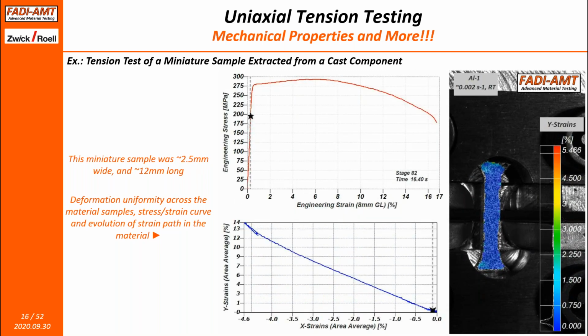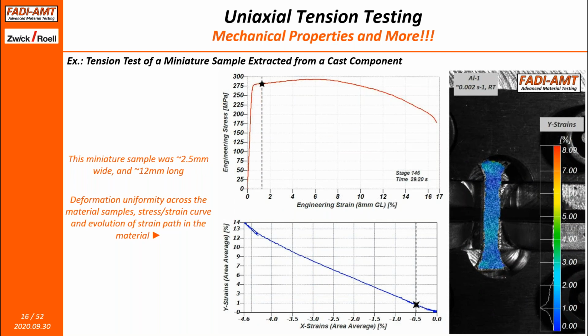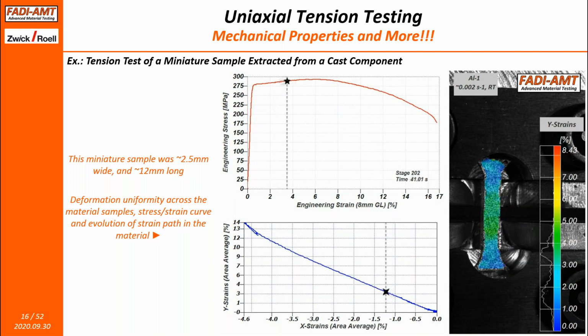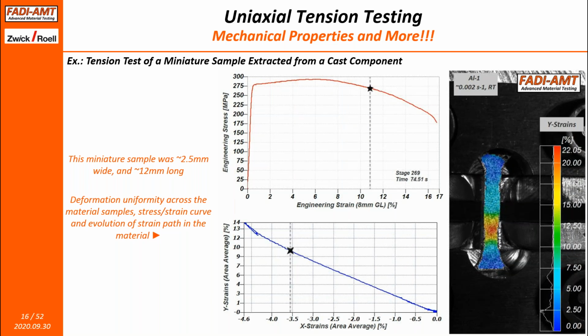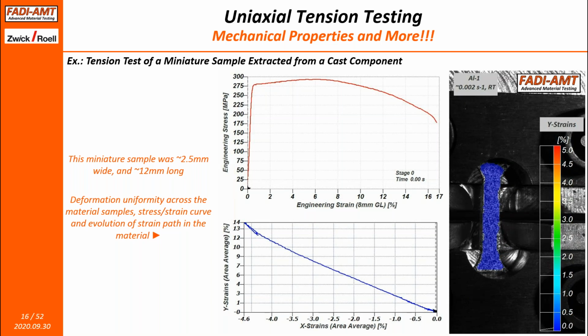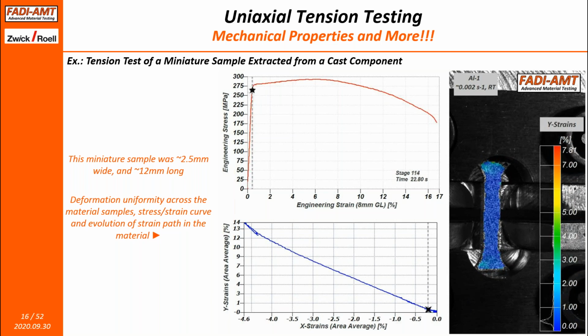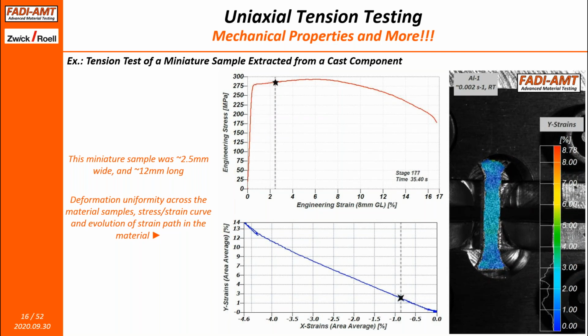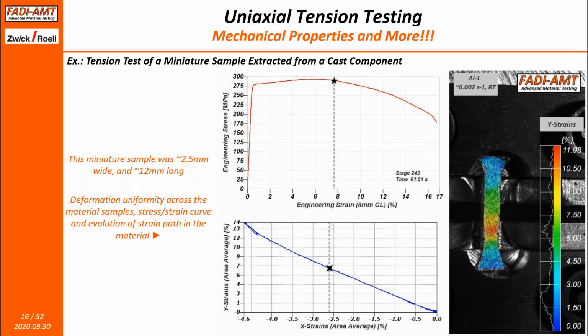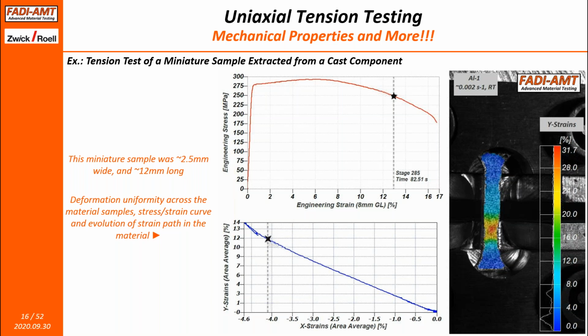Another case here is a miniature sample. This is taken from a cast component, and of course, with the limited location that you can take the sample from, obviously the sample size has to drop. And now the question comes in, can I do this with extensometry? Technically, you should be able to if you have flexibility with the extensometer. Of course, you cannot use clip-on extensometers that easily here, but some of the video and non-contact extensometers can be adjusted to track a smaller length. In this case, it's a 12 millimeter sample, so you could potentially do it. However, again, the limitation stays there, which is the ability to see how the material is deforming and how is it failing under these loading conditions.